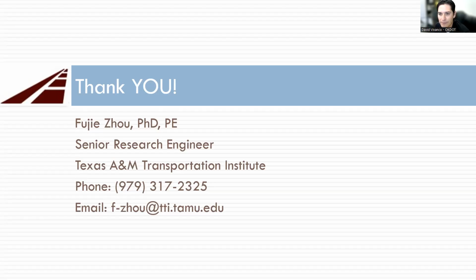Another comment from Tisha from RIDOT. When pulling samples of plant mix, do you age the asphalt any before compaction of IDEAL-CT? Should samples be brought back to compaction temperature? That's a great question. It's a pretty technical question. In Texas, yes, that's a TxDOT required procedure. You sample from the truck at the asphalt plant, bring it into the lab, and set it at compaction temperature. Stay there 2 hours. After that, you measure your Rice value, compact the sample, measure the lab molded density, and the same thing for IDEAL-CT, for IDEAL-RT.